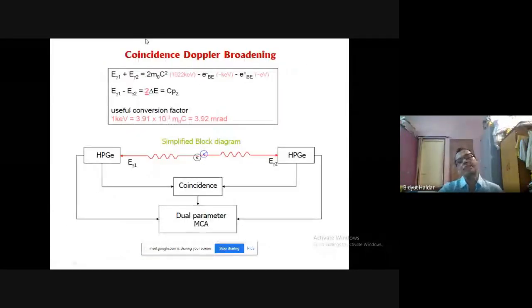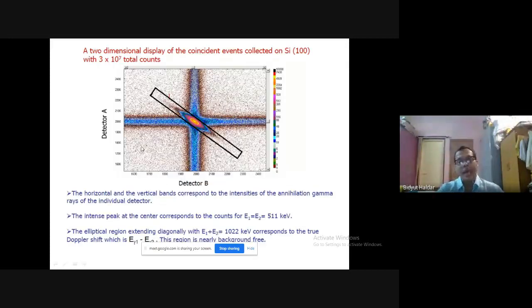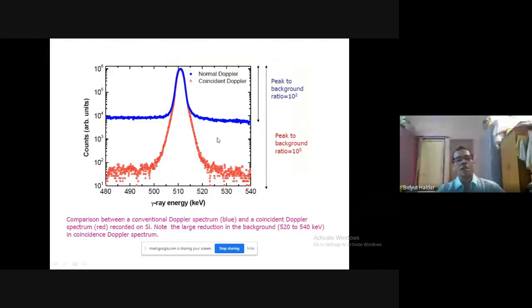Nowadays, we use coincidence Doppler broadening, where both the gamma rays are detected and their energy spectra are overlapped in two mutually perpendicular directions to get a spectrum of this type, and analysis of the central part can give a lot of information. Here you can see the two spectra obtained by a normal Doppler and a coincident Doppler. In the coincident Doppler, the peak-to-background ratio is highly enhanced, which gives a lot of information about the type of defect present in the sample.